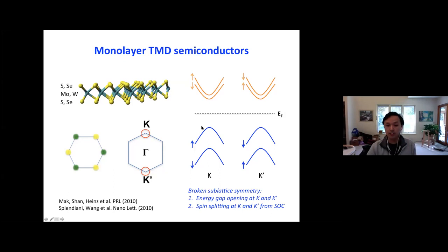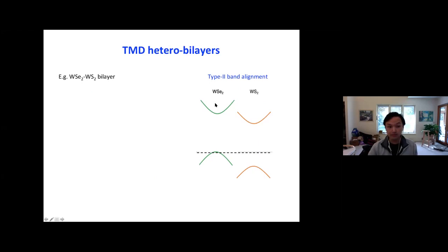And because of spin orbit coupling, due to the relatively heavy transition metal atom, the spin states are split at the K and the K prime point, but they are opposite split to preserve time reversal symmetry. Okay, so this is a very simplified band structure of the system, but it describes the low energy physics quite well. So let's consider what happens when we put two TMD layers together.